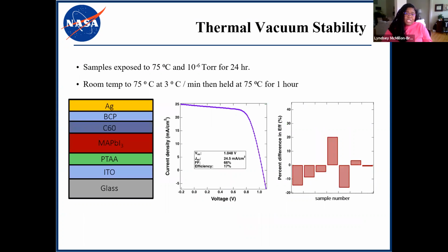Now we expand on this test by taking baseline solar cells and exposing them to thermal 75 degrees C and vacuum 10 to the -6 torr stress conditions for 24 hours. And we also observed degradation here.